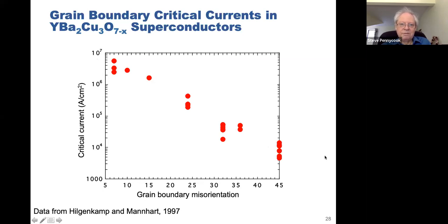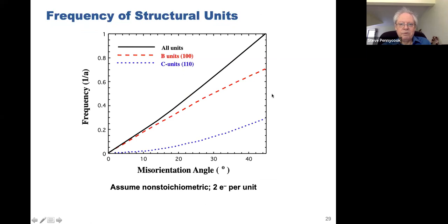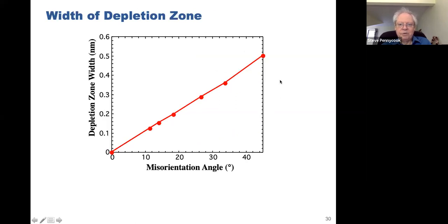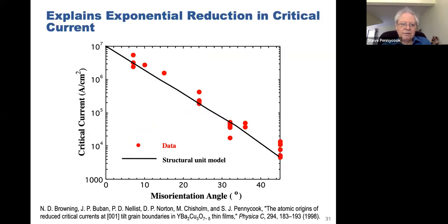Well, we thought for a few years, in fact, we know the structure of these boundaries because we can predict them. We know what kind of units they are, and the number of units goes up with misorientation angle like this. Let's assume 2 electrons non-stoichiometry per unit, for example, and let's plot the depletion zone. And since the number of units goes up linearly, so does the width of the depletion zone, and a supercurrent is going to tunnel across that. And so it's pretty natural. If you have a tunneling effect, the critical current is going to go down exponentially. So we were pretty happy to see this fit between their results and our structural unit model prediction.